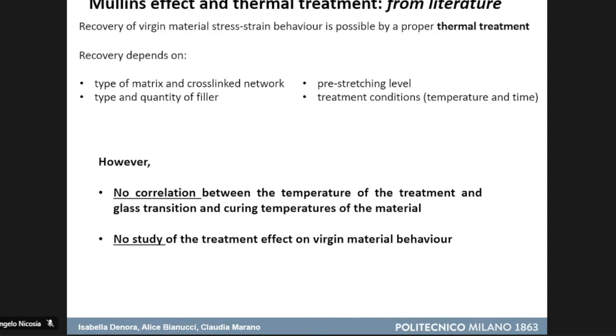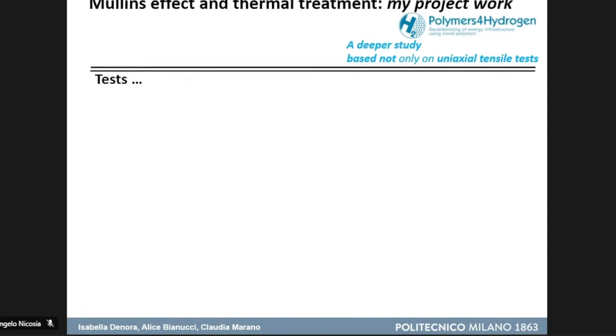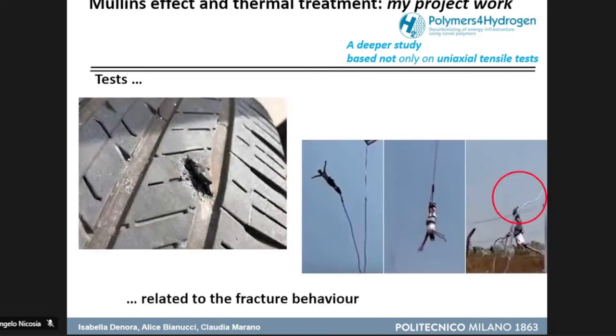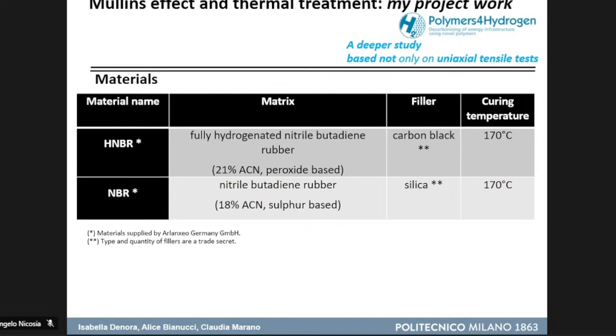In fact, we know that if we apply thermal treatment, some further reticulation or chain scissions can occur in the material. So in my work, I have performed an analysis on the effects of softening and of thermal treatment on softening, but not performing just a uniaxial tensile loading test, but by seeing the effects on fracture behavior of the materials, because we know that these materials are applied in objects that can be subjected to some failures, such as tires and also bungee jumping cords. The materials that I have investigated are one HNBR filled with carbon black and one NBR filled with silica.